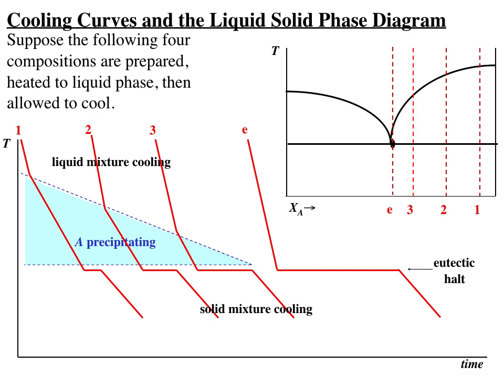So I move along the curve from the composition of the mixture of the isopleth 3 towards the eutectic. I'm getting richer and richer in B as the mixture approaches the eutectic. Now, eventually, I get to the same temperature of the eutectic halt. But notice I have a shorter eutectic halt because I have less of the mixture of the eutectic composition. Finally, when that eutectic is all solidified, then the solid can cool along after another discontinuity in the curve. I can diagonally cool the solid.